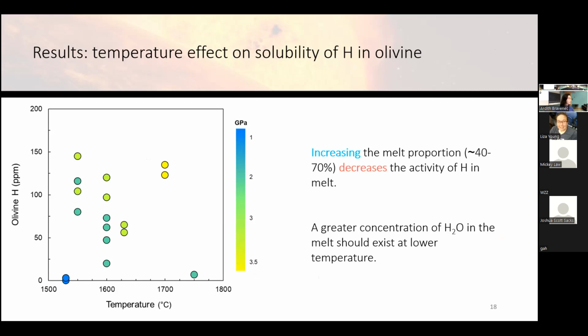But the reason for this is simply that these crystals don't exist in a vacuum. They exist embedded in these silicate melts. So if you increase the melt fraction as you increase temperature, you actually decrease that hydrogen component, meaning that water activity decreases and you have less water available to infiltrate those crystals. So actually, again, this is a result that makes sense.